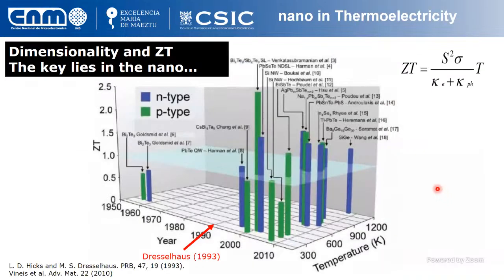One milestone in thermoelectricity was presented in 1993 by Professor Mildred Dresselhaus. This theoretical study predicts that reducing dimensionality would increase this figure of merit by lowering principally K. Before this prediction, thermoelectric materials were bulk-based, mainly chalcogenides, with figure of merit around 0.5. After Dresselhaus theoretical work, nanostructured bismuth material thin films, and even silicon-based nanotubes, nanowires were developed, achieving figure of merit around 2.